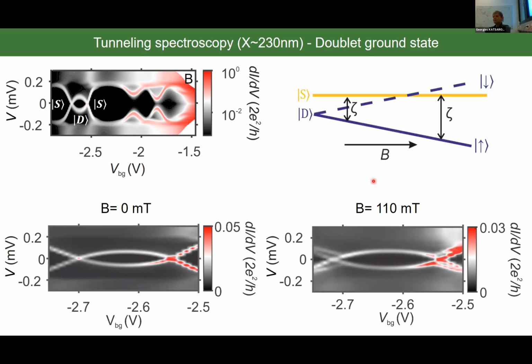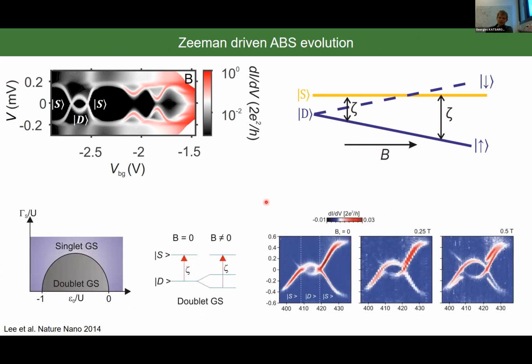How can we understand it? If we have a doublet ground state and you crank up the magnetic field, the doublet ground state splits. And since in our measurements we measured excitation from the ground state to the excited state, zeta is increasing with magnetic field. And that's in agreement with the measurement which Eduardo Lee has done back in 2014, the so-called Zeeman-driven Andreev bound state evolution. In the doublet state, you can see very nicely that also in his measurement, the Andreev bound states go up in energy.